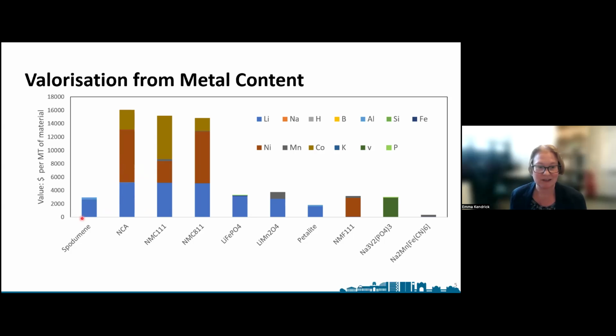But if we look at the lithium content in spodumene compared to the lithium content in some of our battery materials, per kilogram or metric ton they actually contain significantly more quantity or value compared to our primary materials. Petalite is a clay, which also is a primary material. And even some of our very low cost materials like lithium iron phosphate and our lithium manganese spinel, these still contain a good quantity of lithium in comparison to our spodumene rock. So it kind of makes sense that we should look at recovering lithium from our secondary ores as well as our primary ores. In addition, the value of our transition metals is significantly larger.